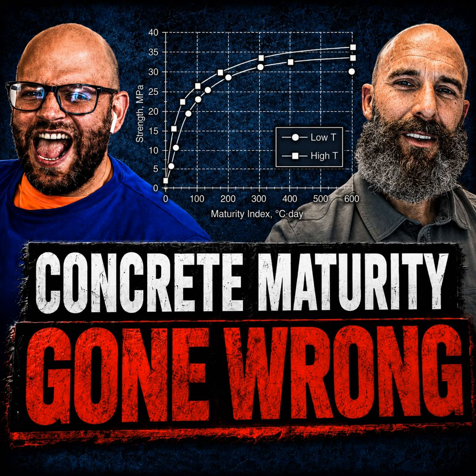But in that equation, which is a delta T, a change in temperature, your time and temperature minus your datum temperature, the datum temperature is what most people assume incorrectly, or totally ignore. What is datum temperature? Datum temperature is the minimum temperature that you need to kick off the kinetics of cement hydration. I'm simplifying it, squishing it, for all those that are listening.